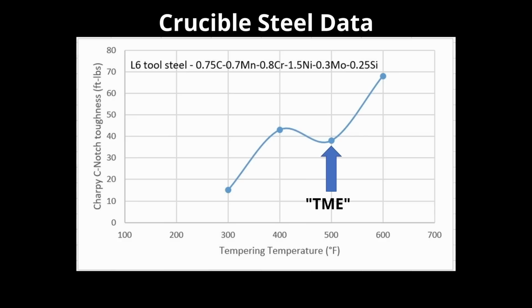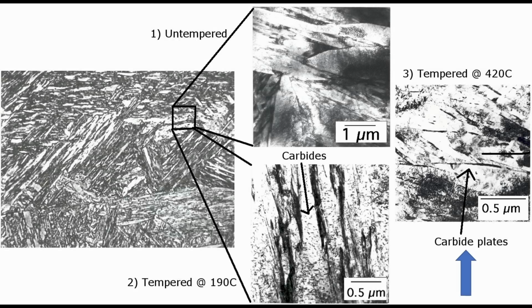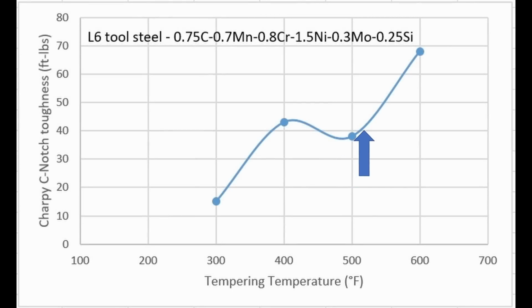So tempered martensite embrittlement, that is when you get coarse carbide particles that form when tempering at those temperatures. So when you temper at low temperatures, the martensite softens by precipitating carbon out as little tiny carbides. And as you temper hotter and hotter, those carbides get larger and larger. When they get coarse enough, they actually start to decrease your toughness, even though the hardness has also been reduced. Then when you continue on tempering up to hotter temperatures like 600, 700 degrees, the toughness starts to go up again because the coarse carbide particles aren't affecting things as much as just softening your overall steel.